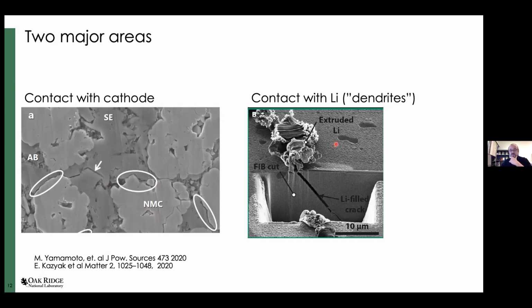in Osaka. And they fail in contact with lithium, what we collectively call dendrites. Trying to stay away from this term because these are really not always fractal structures typical for dendritic growth, and we carefully call them lithium filaments. But in any case, contact with lithium, a seemingly very ductile material, can lead to the fracture of the solid electrolyte and propagation of those lithium filaments which short the cell. So the idea of moving away from separators that are not strong gets diminished if you have an electrolyte that fails in a brittle manner.